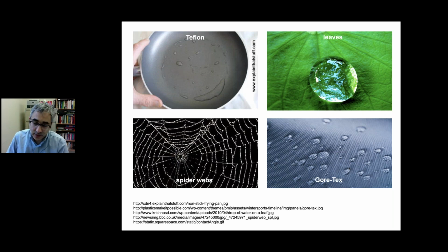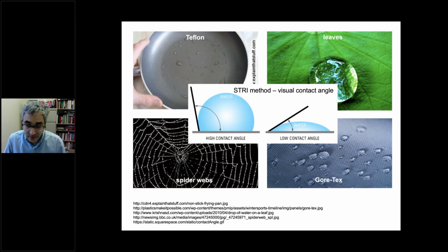So how can this be evaluated? From a very crude perspective, you could simply put a drop of water on the material and make an assessment with your eye to see whether it's starting to spread on the surface or if it's still beading up. In fact, the STRI method is nothing more than a visual inspection of the contact angle. In the lab, you can look at this more analytically by taking a picture through a microscope, going into Photoshop, and drawing a tangent line to characterize this contact angle. There you can come up with a definition: less than 90 degrees is hydrophilic, more than 90 degrees is hydrophobic. So there's a 135 degree contact angle for silicone rubber, for example, when it's clean, and when the surface is aged or contaminated with algae, the contact angle drops.